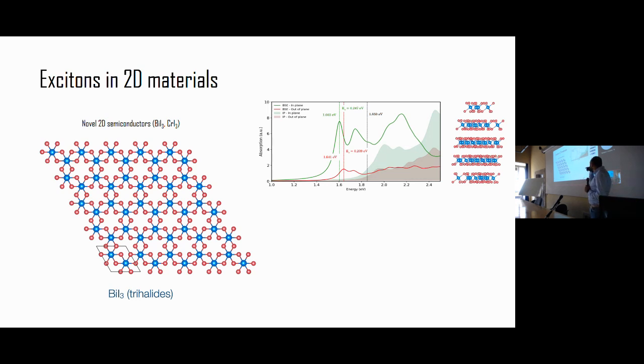So you reduce the screening really a lot, and then you are starting to be like in a molecular material, no? And then already in the bulk that is plotted here, you have a very large binding energy that is around 0.24 eV. This is a bulk, infinite material, but it has the binding energy that you can find in a single layer of MoS2.